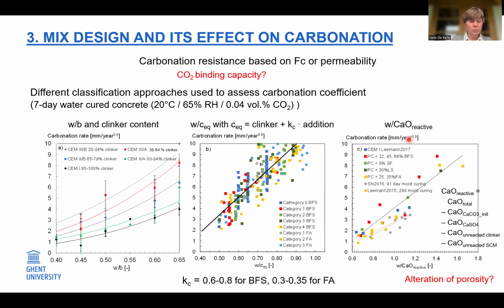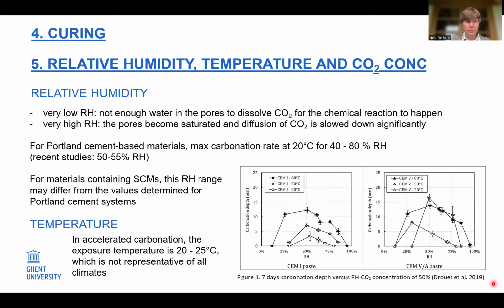And then thirdly, we could use the buffering capacity approach, where we use the water over reactive calcium oxide as the main indicating factor. It's most scientifically sound, but then you have to know or calculate this reactive calcium oxide content, and that may not be so simple. But it is easier with this approach to include new materials or to apply it also on new materials. Still, the effect of the alteration of porosity is in this way little accounted for.